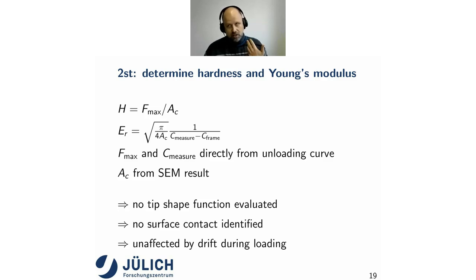Once you have the frame stiffness or frame compliance, however you want to call it, you can calculate the hardness and the Young's modulus. The hardness, well, that's according to textbook, force divided by area. The Young's modulus is a reduced Young's modulus, but if you use the Sneddon equation, which goes into the traditional way of calculating the Young's modulus during nanoindentation, you subtract the compliances, and then from all the data that you have, you can calculate hardness and reduced Young's modulus. And just as a reminder, the contact area we obtain directly from our SEM results.